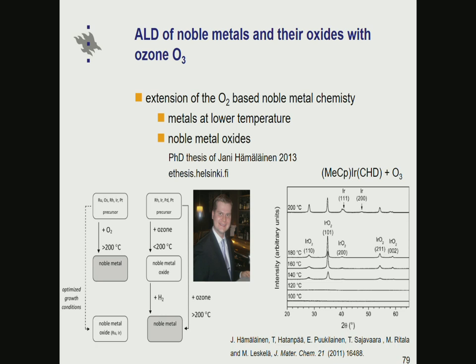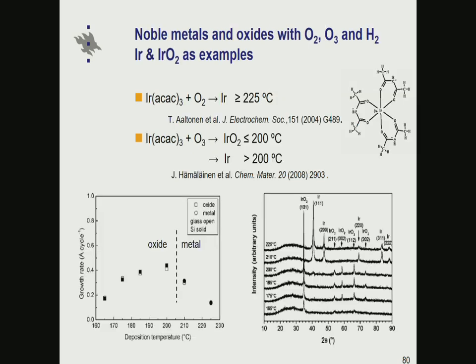Okay, then we extended this chemistry further later by replacing oxygen with ozone. That made it possible to also deposit noble metal oxides at low enough temperatures where these oxides are stable. On the other hand, when going to higher temperatures, we actually got metals also with ozone. And this shows an example of how one can tune the resulting film composition using oxygen, ozone, and hydrogen in proper combination. So iridium acetylacetonate, a beta-diketonate, reacts with molecular oxygen only at about 225 centigrade, producing metallic iridium. But if one uses ozone, at those temperatures where it doesn't react with O2, one is able to deposit iridium dioxide. On the other hand, when exceeding 200 centigrade, with ozone we also get metallic iridium.